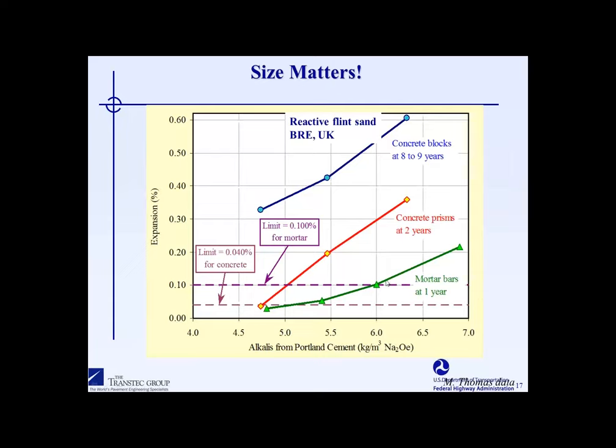And this is basically showing mortar bars in green, concrete prisms in red, and concrete blocks here in blue. And what you see here is that the larger the specimen, the higher the expansion level we get because of the reduced leaching with the larger specimen sizes. And you'll see that the larger the specimen, the lower the alkali content required to drive the reaction. So size does matter in this case, and it is a limitation, particularly when we're looking at the concrete prism test relative to field data and concrete blocks.